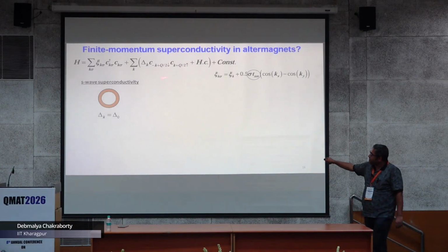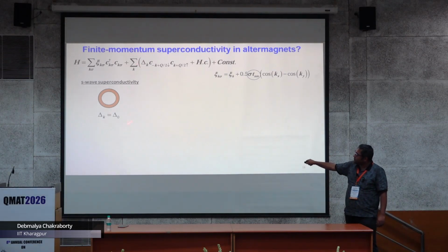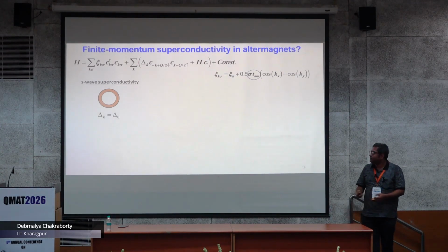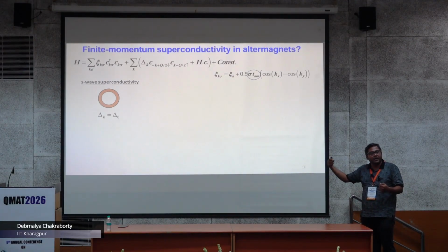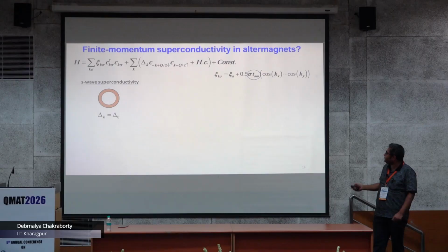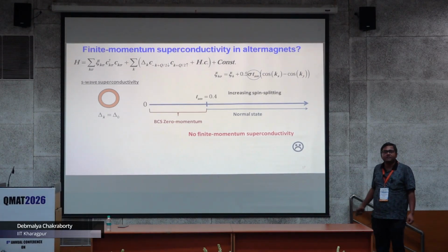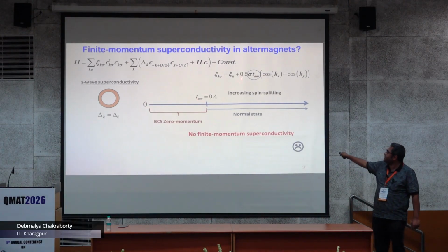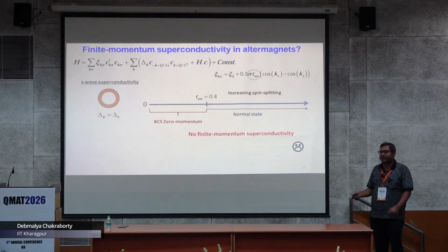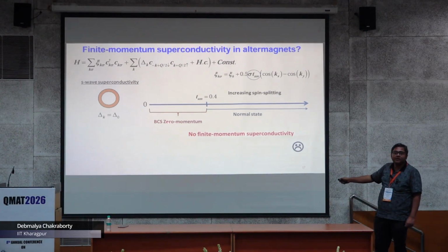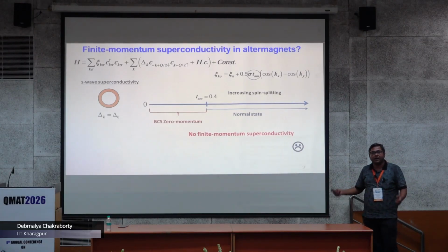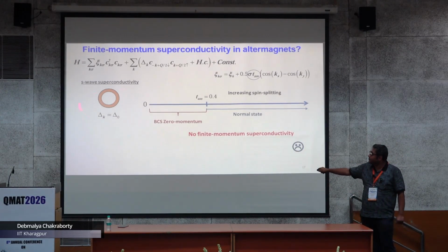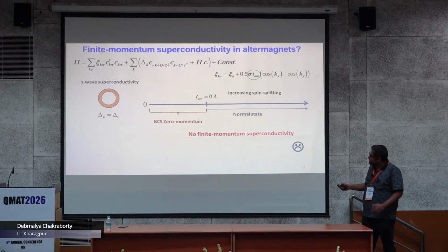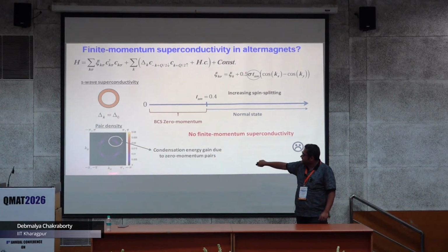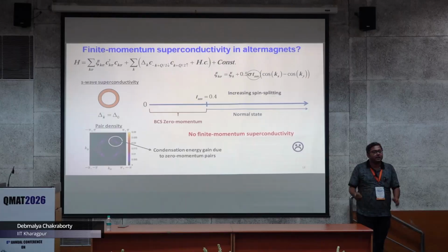What we start with is the superconducting order parameter, which is constant in momentum space, s-wave. If it is s-wave, we try to change t_AM and see if we can find finite momentum superconductivity. To our disappointment, if we keep on increasing this t_AM, the altermagnetism strength, we go from zero momentum to a normal state. There is no finite momentum superconductivity if you take an s-wave superconductor. The reason is very simple. If you look at the pair density, that means the expectation of c dagger.